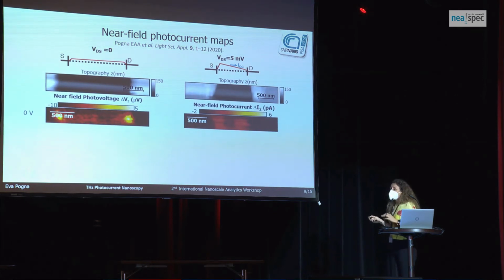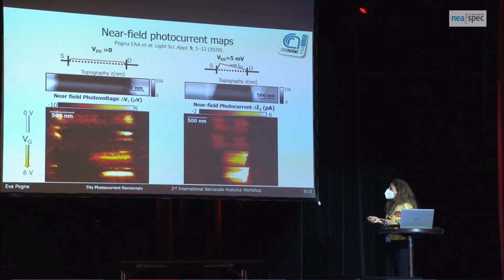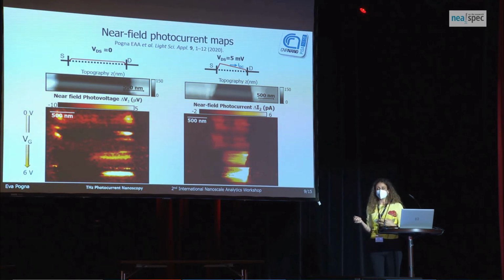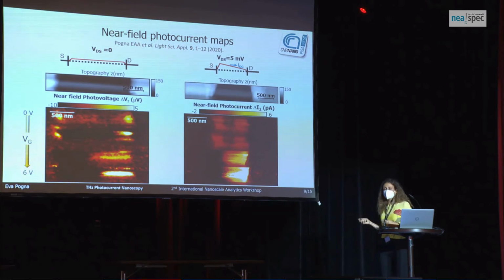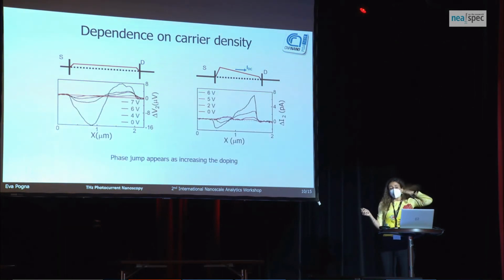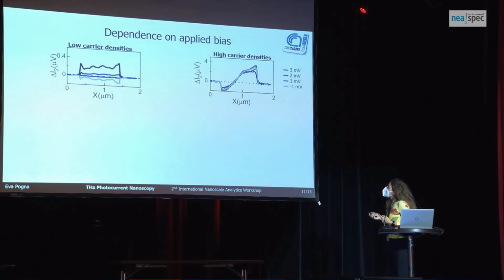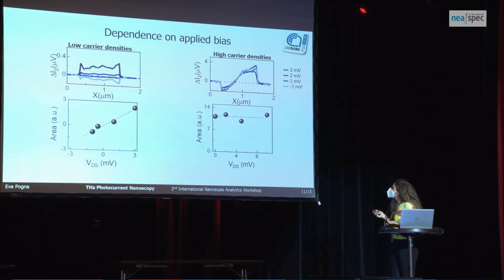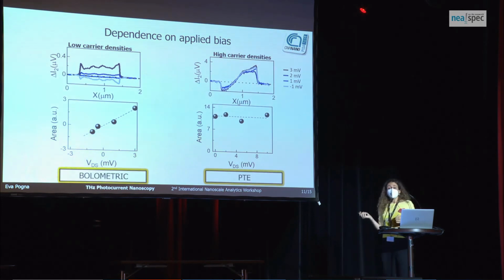And without applying any bias, the first response is a current with a constant polarity along the nanowire. So, as we said, a bolometric fingerprint. But as we increase the gate voltage, we always found a threshold at which the photocurrent profile completely changed, with the appearance of a clear polarity change at a position along the nanowire. So we see that, at the high carrier density regime, the photothermoelectric effect or the plasma wave effect are dominating. In order to distinguish between the two, we analyzed the variation with the bias, and we saw that in the high carrier regime, where we have the change of polarity, the photovoltage is constant. So we can say that in this regime, the response is dominated by the photothermoelectric effect.